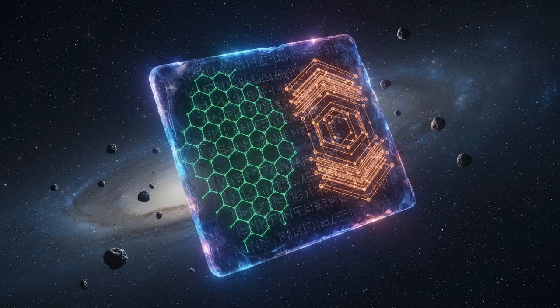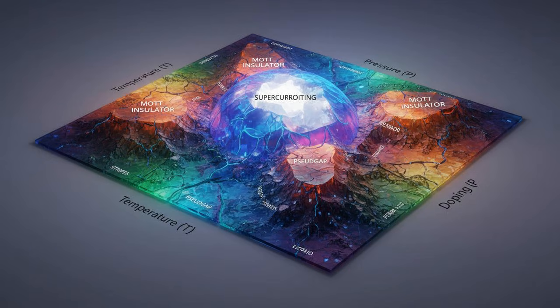This suggested that the mechanism behind this superconductivity was something new. It looked suspiciously like the mechanism found in cuprates, those mysterious copper oxide ceramics that hold the record for high-temperature superconductivity. Suddenly, graphene wasn't just a material, it was a Rosetta Stone. Physicists realized that if they could solve the puzzle of twisted graphene, they might unlock the secrets of room-temperature superconductivity. This discovery birthed the field of Twistronics. It represents a fundamental shift in how we engineer matter.